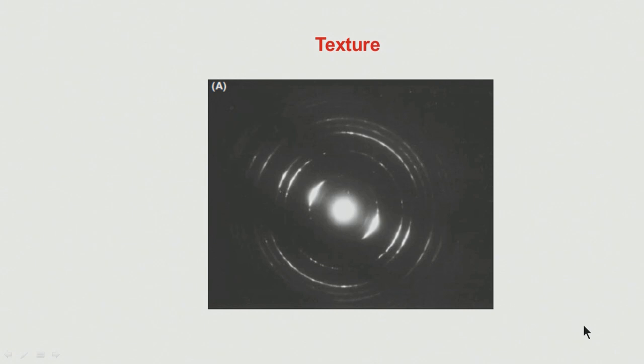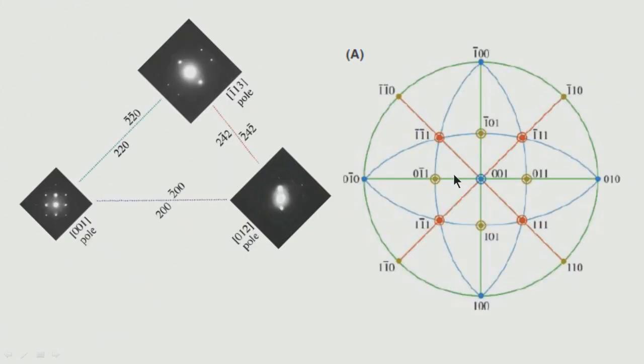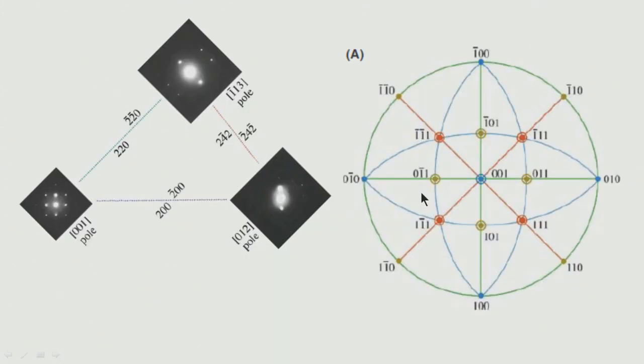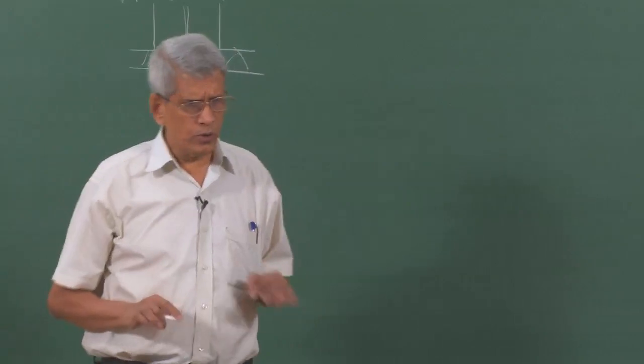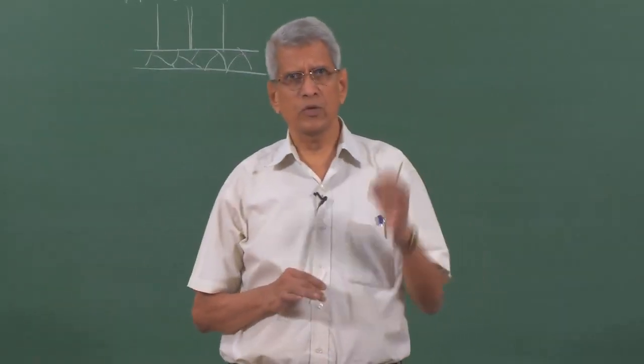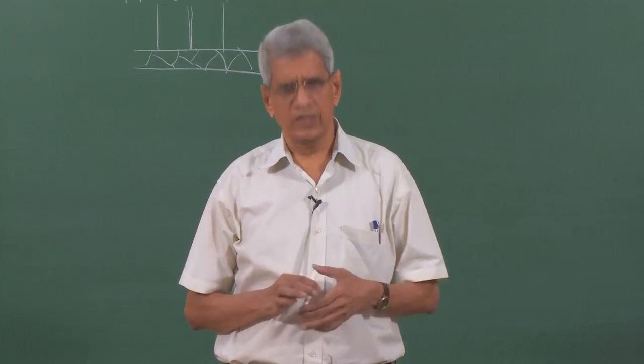If the sample is heavily deformed, texture occurs as studied in phase transformation courses. In textured samples you do not see a complete ring, but streaking of many of the diffraction spots can be observed in the diffraction pattern. To get complete information about a sample, getting a diffraction pattern or microstructure in one orientation alone is not sufficient.